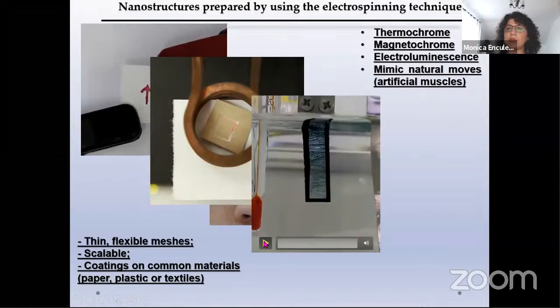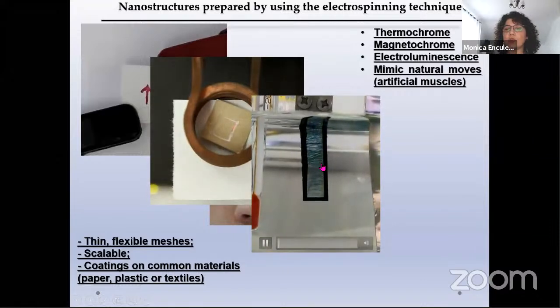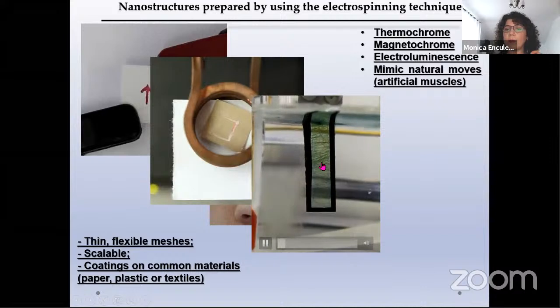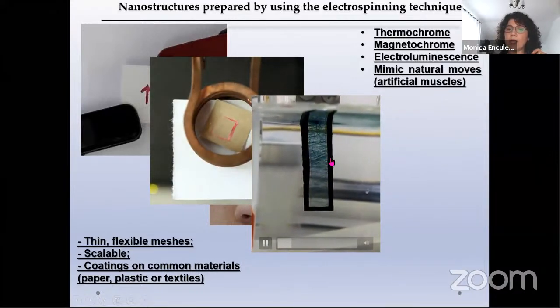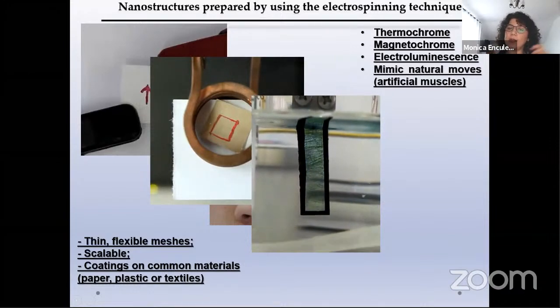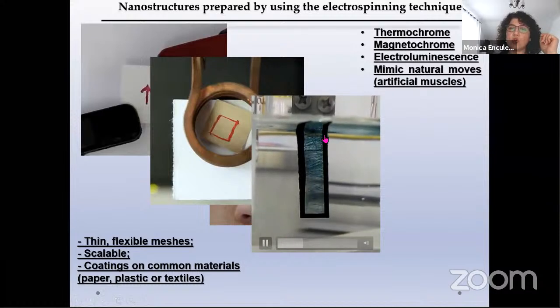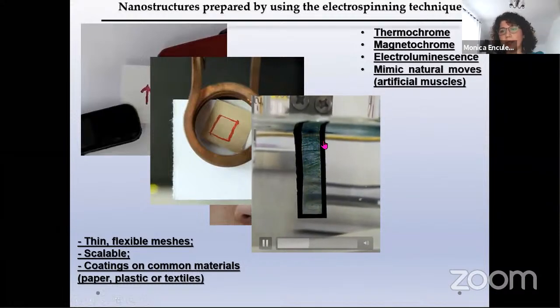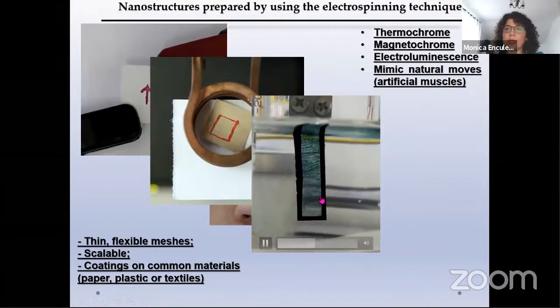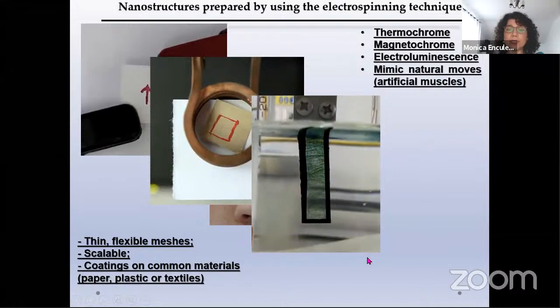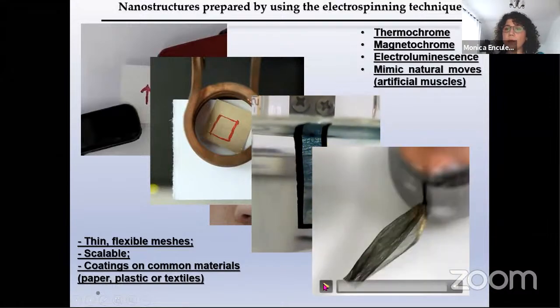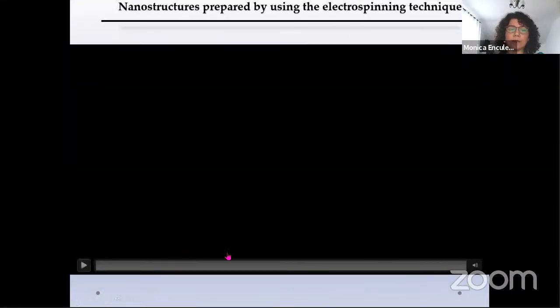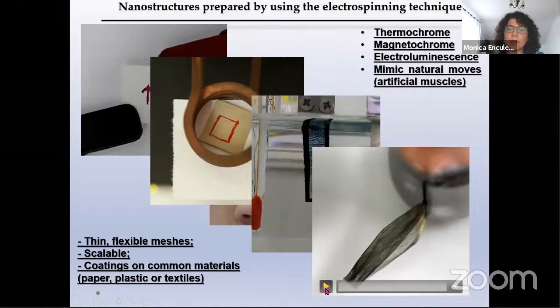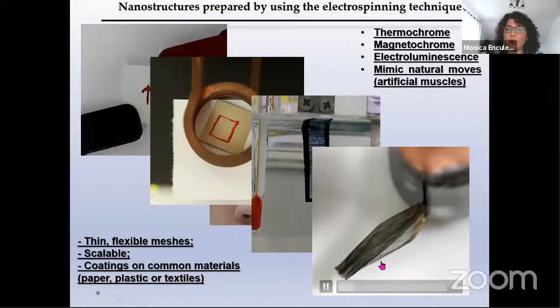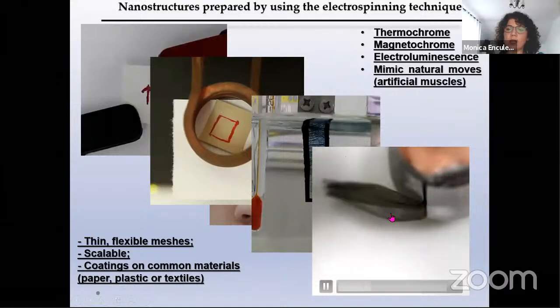And as I explained earlier, with polyaniline, we can make electroluminescent fiber, because by playing with the voltage, we can make this coating of polyaniline change in the luminescent form. There is an emitting type of polyaniline that is luminescent. And further, we can play with the coatings and we can mimic the muscle, because by applying a voltage on our nanostructures, we can make them move.